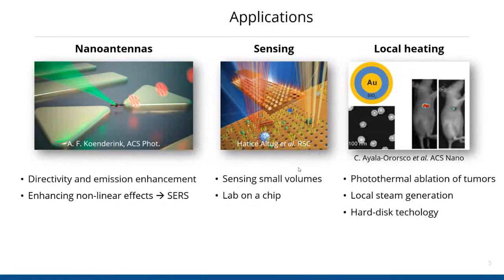The applications of plasmonics all revolve around the ability of plasmons to confine light to very small volumes. Plasmonic systems can strongly enhance and direct emission from single emitters such as single photon sources, molecules, and quantum dots. Because structures confine light to small volumes, you can also create very high electric field amplitudes, which is great for enhancing nonlinear effects such as Raman scattering, second harmonic generation, and four-wave mixing.